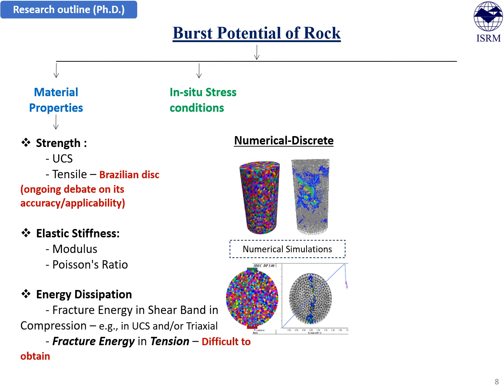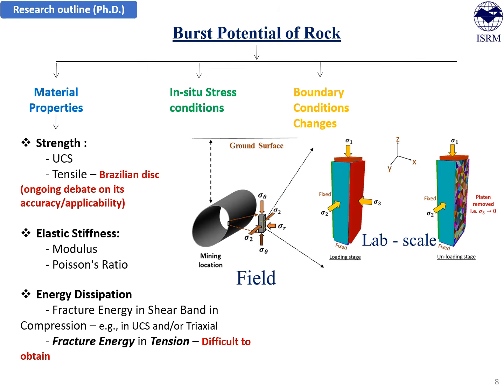The other factor is in situ stress conditions, followed by changes in boundary conditions. Now, when we excavate, obviously, we provide a free face to the rock around the excavation to dilate. That change in boundary conditions enables rock to release its excess strain energy, and the amount of excess strain energy governs the magnitude of bursting, which needs to be evaluated while calculating the burst potential of rock.